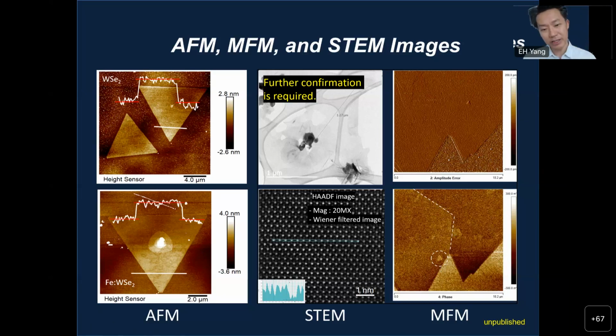If that's the case, we confirm that this is a room temperature ferromagnet, okay? But then recent work, which we have the measurements, but from the collaborator group, so I cannot put them in this slide, and it confirms that the iron doped tungsten diselenide is a very strong ferromagnet. We need further work, and I cannot show it in here publicly.